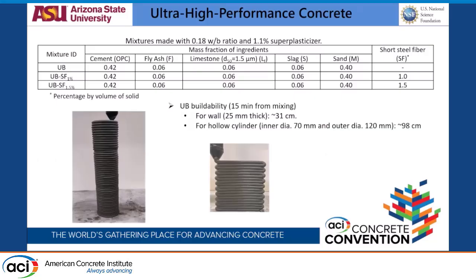As the start, we had to create a UHPC mix that's printable. For the shortness of the presentation, I'm not going to give you the details of the mixes, but we tried different binary and ternary formulations to reach a mix with 60% by mass of binder and 40% by mass of aggregate. The aggregate is just medium sand with a 0.6 mm particle size. In the binder system, we have 70% cement with 10% each of fly ash, limestone, and slag. So it's 70 cement versus 30 replacement agent.